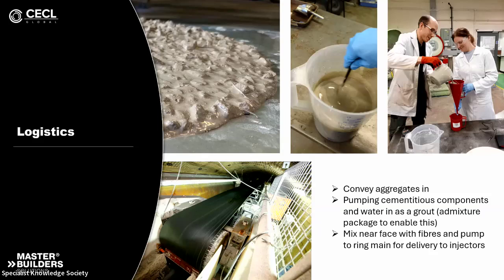So what we're proposing is that the coarse aggregates and the sand are taken to the face in conveyors, and the cementitious component and the water is in a slurry. The little video you saw of Henry and my other colleague Era looking at the viscosity and the rheology of these grouts shows that we're absolutely confident that the open time for these grouts will allow us to pump the cementitious materials to the face and mix with the aggregates at the face.